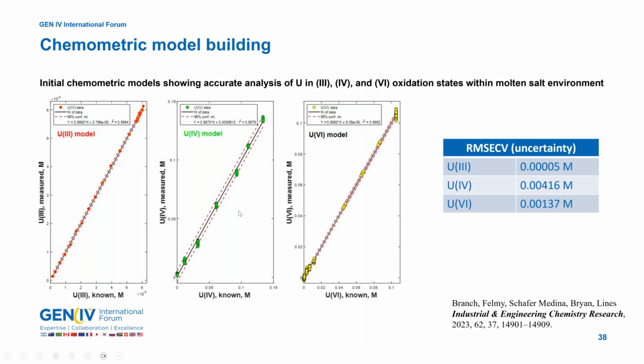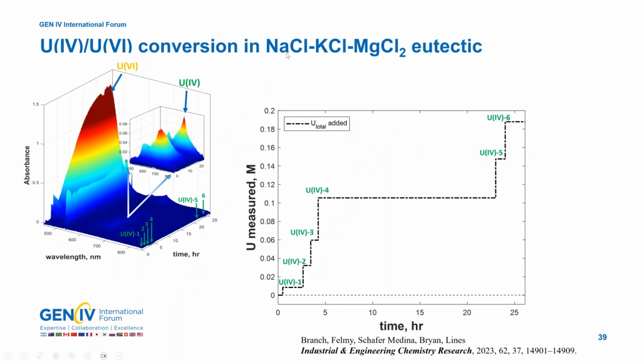So those measurements and others were used to then produce chemometric models. As shown here are several where the measured concentration from our model is on the y-axis, and the known concentration from gravimetric analysis is shown here on the x-axis. So we have models that measure for uranium-3, uranium-4, and uranium-6. And all of these, we have a fairly good root mean square error of prediction in the millimole concentration range or less.